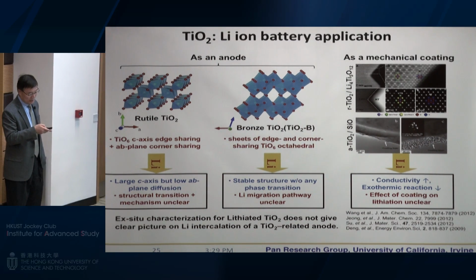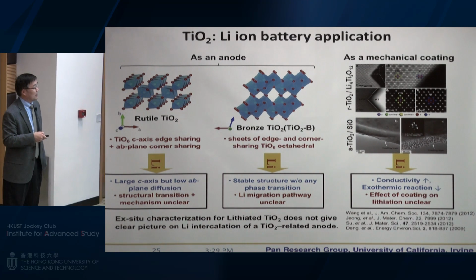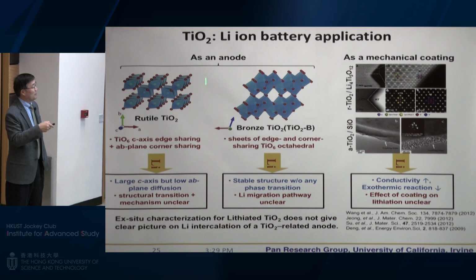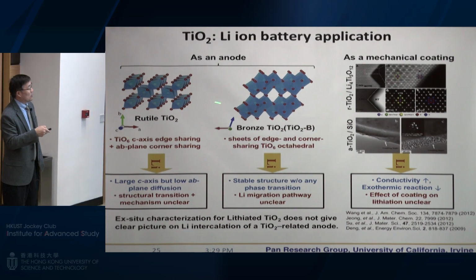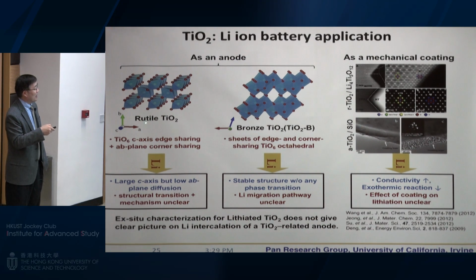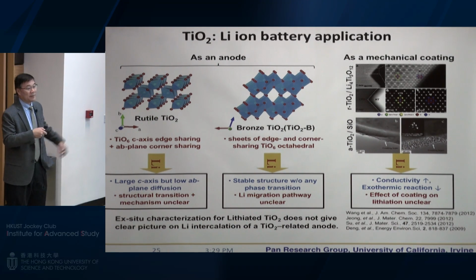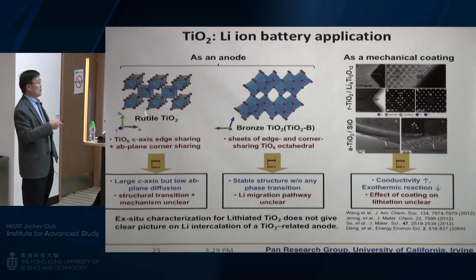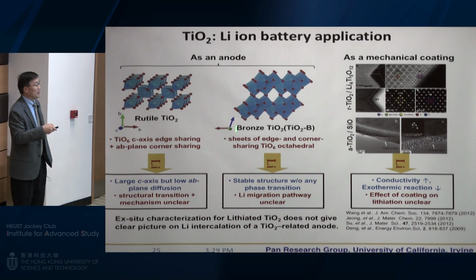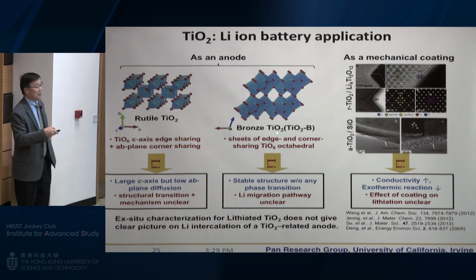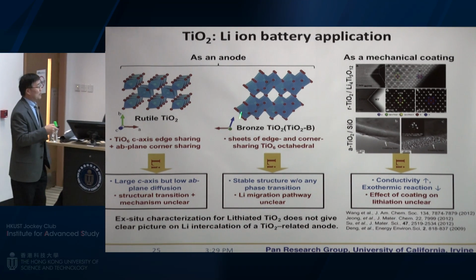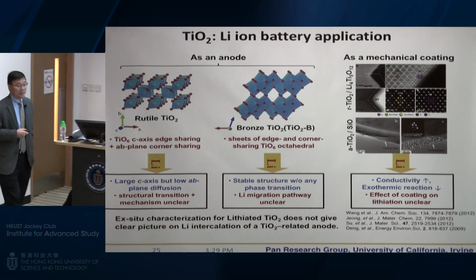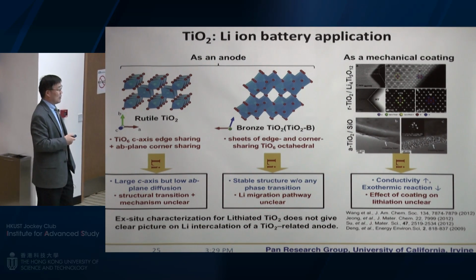So I'll just show a little bit of our recent work on this. We studied the nanowire of rutile, and also the nanostructure of the bronze, because the structure of these two different TiO2 phases is different. This one has edge sharing on the C-axis and corner sharing in the AB plane. Then the lithium diffusion is different along the C-axis versus the AB plane. Right? Another structure that has recently become more interesting is the bronze structure, which is not very common. But this structure has a much larger open space, so people expect the lithium diffusion will be much easier, higher diffusion.